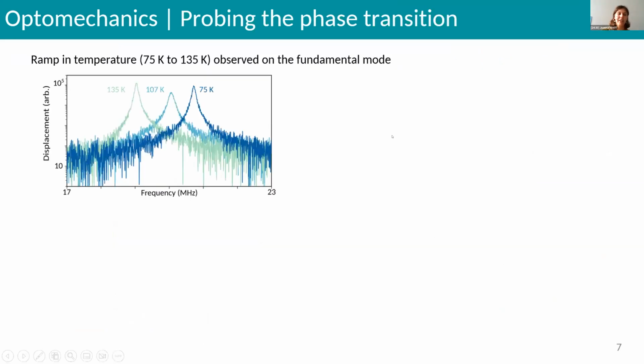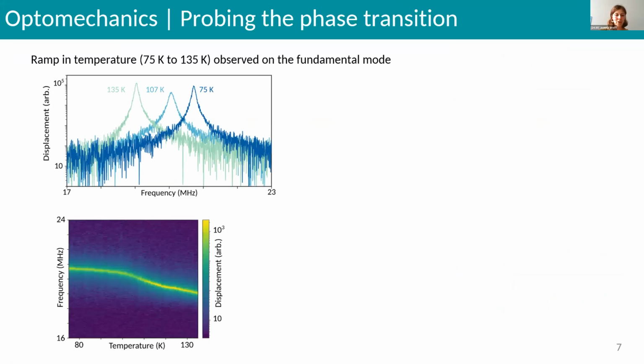There are here three spectra taken at different temperatures, and you can already see that there is a shift in frequency of this mode. If we plot all the modes together, like seen from above, you have here the temperature and here the frequency. You can see already that there is a different slope between these two lines, and it will be the sign of the phase transition.